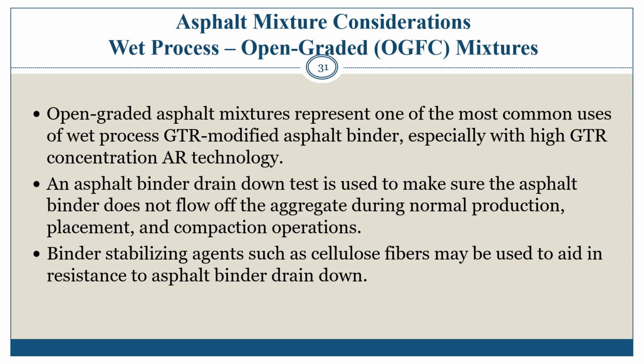Asphalt mixture considerations for wet process open graded friction course mixtures, or OGFC mixtures. Open graded asphalt mixtures are more common with wet process GTR modified asphalt binder, particularly with AR technology. A common test for OGFC and SMA is binder drain down to ensure that binder does not flow off the aggregate during normal production, placement, and compaction. Stabilizing agents are often used to aid in resistance to asphalt binder drain down. Sometimes warm mix additives may be used with GTR modified systems, allowing lower temperature, which aids in prevention of drain down. It is important to consider the contribution of binder stabilizing agents to mixture durability before foregoing use of these stabilizing agents.